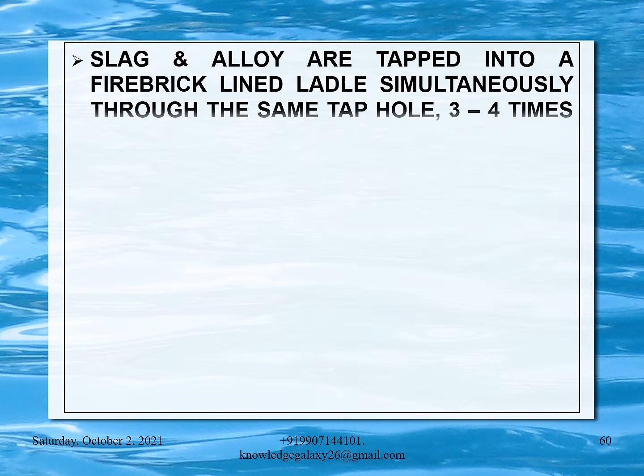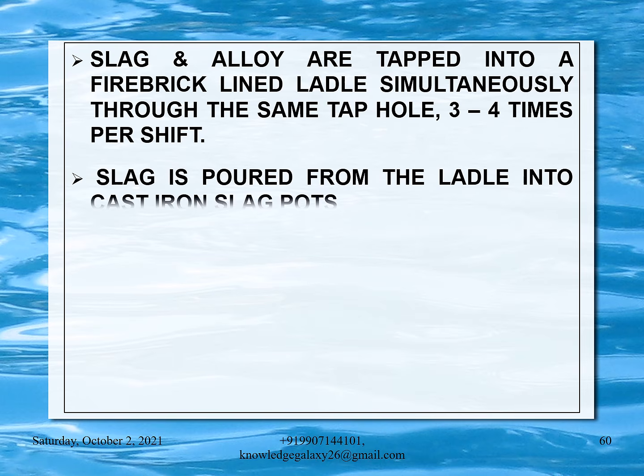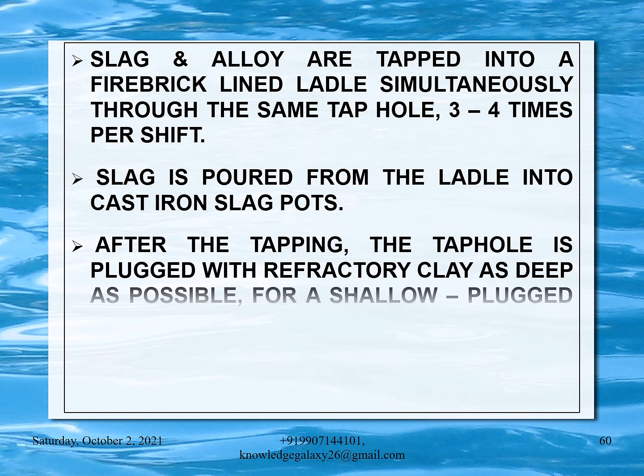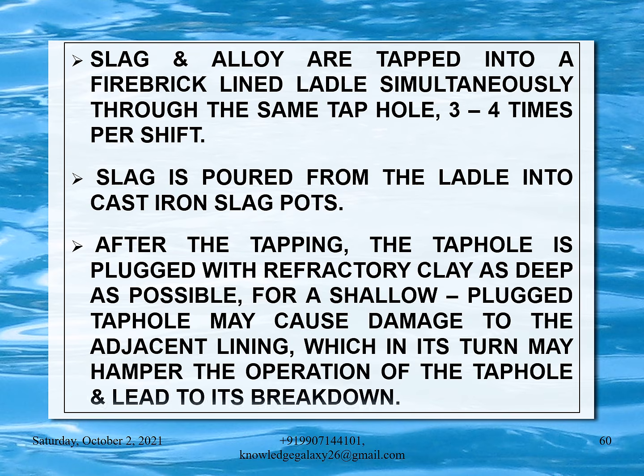Slag and alloy are tapped into a fire brick lined ladle simultaneously through the same tap hole 3 to 4 times per shift. Slag is poured from the ladle into cast iron slag pots. After the tapping, the tap hole is plugged with refractory clay as deep as possible, for a shallow plugged tap hole may cause damage to the adjacent lining, which in its turn may hamper the operation of the tap hole and lead to its breakdown.